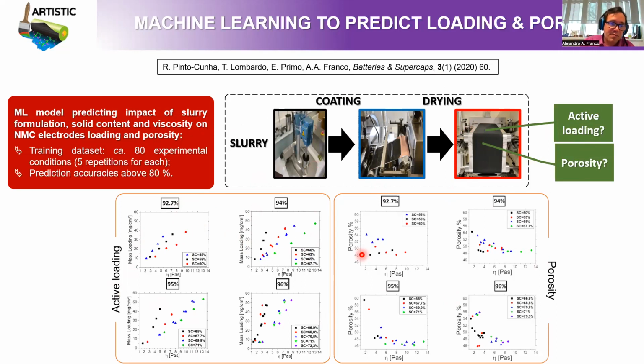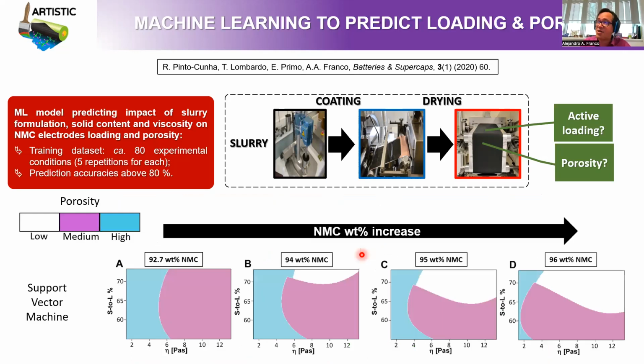And then what we performed is an application of machine learning, a supervised machine learning technique called support vector machine, which allows transforming these noisy data sets into something that is more understandable or readable by the experimentalists, right? Basically, this support vector machine technique allows transforming this cloud of points into phase diagrams for battery manufacturing. And here you see an example of a result that can be obtained with this technique. So here you see the impact of the formulation, that means the amount of NMC that you have in your slurry in weight percentage, the impact of the solid content of your slurry, and the impact of the viscosity of the slurry on the porosity that you will get in the electrode after the drying process.